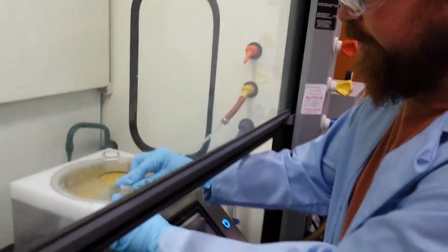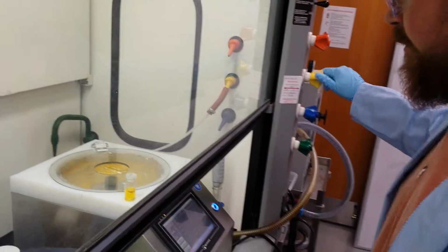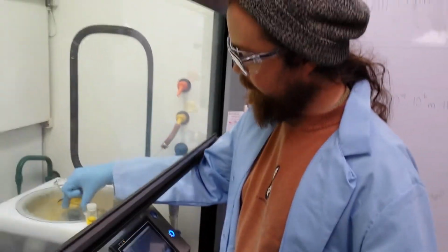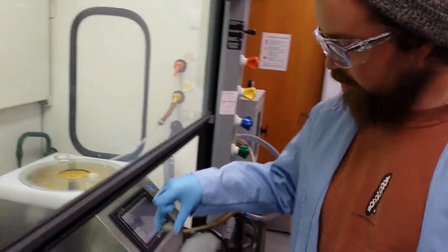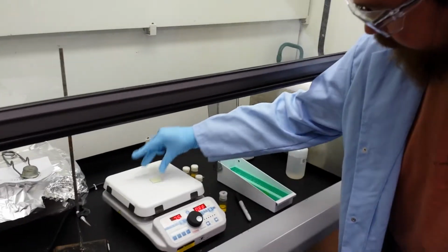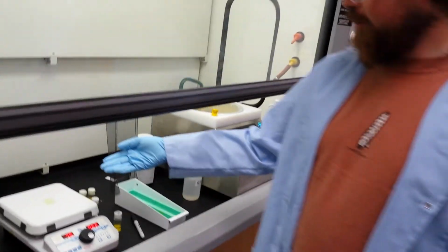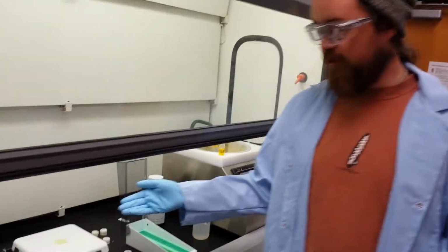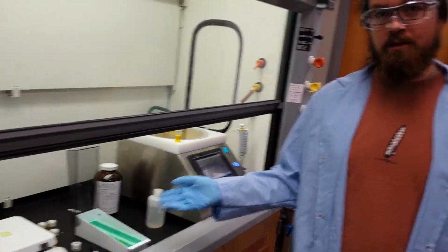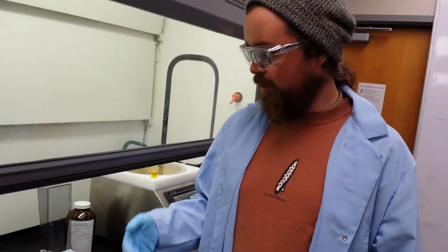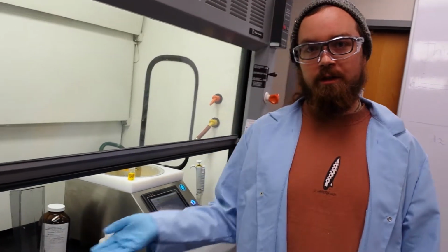Now that the film is done spinning, all we have left to do is turn off the vacuum and transfer our film to the annealing stage so that the solvent can evaporate off. And now that we have the film here on the annealing plate, in about 20 minutes that's going to be set and the solvent's going to be evaporated off. And that's how you make spin-coated films out of chalcogenide glass.